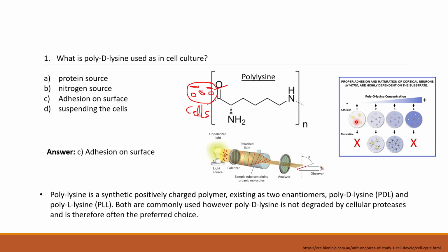Here you can see at the least quantity the cells are not adherent, but at the same time in the highest quantity you can see they are not properly adherent. Even though they might go and stick to the plate, they are not properly adherent, which means they will not spread out and show their specific morphology. Like you can see in 2 and 3, these circular cells, whenever they're in suspension, cells will always be circular, spherical, regardless of their actual morphology.